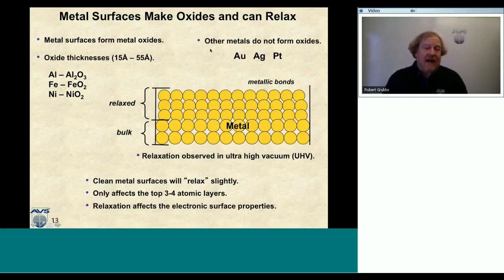The other thing that can happen to a surface, and this really happens in ultra-high vacuum, is that the metal atoms can actually relax. So we know that silicon surfaces, we have the bonds that are high energy, and they'll tip over and sort of bond with one another to lower the surface free energy. Well, metal bonds in ultra-high vacuum, if I take a metal surface and I cleave it, what's going to happen is that those few atoms on the surface, maybe 3 or 4 monolayers, are going to shrink, and they're going to collapse into the surface. And that really has to do with how a metallic bond is actually formed. And obviously in the bulk, they stay the same, but the top surfaces relax.